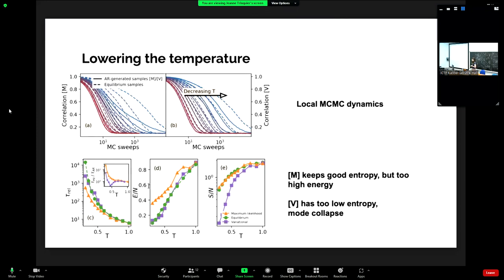And then we tried to lower the temperature, and it failed. To check if your model is good, you can do many things. For example, you can take one sequence generated by local MCMC, so a real equilibrium sequence, run some local MCMC dynamics on it, then do the same with one sequence generated with your generative model, and check that they exhibit the same kind of dynamics. In those plots, the dashed lines are the dynamics of the true equilibrium sequences, and the solid lines are the dynamics of the generated sequences. You see that at high temperature the dynamics are very similar, so the model is good, but when you decrease the temperature a little bit, it becomes very different.